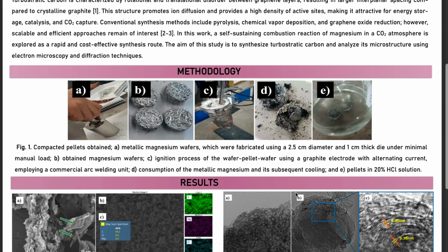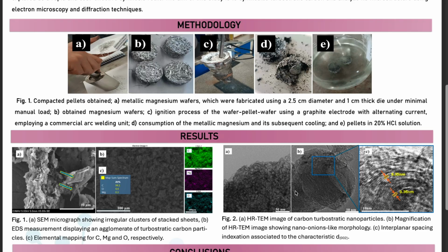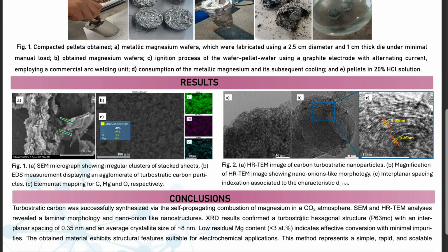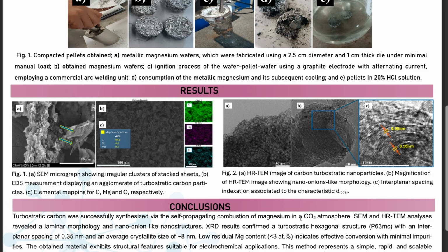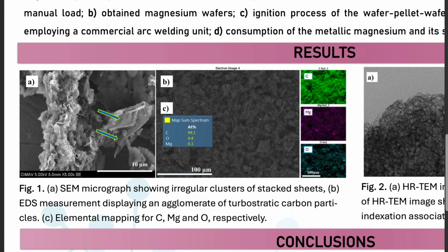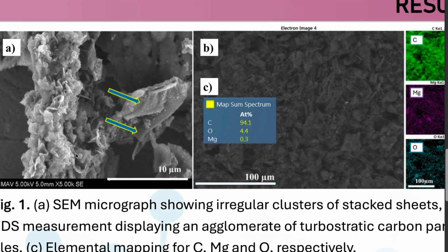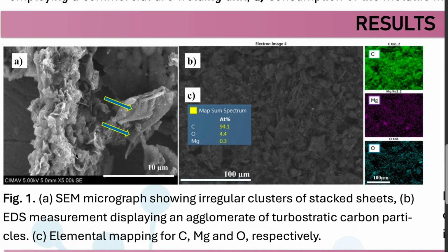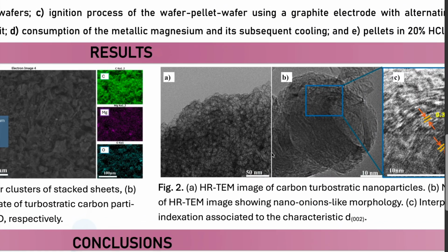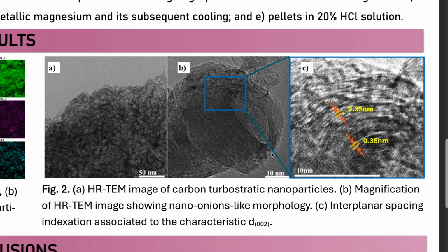Now, turning to the results section, we evaluated the structural and morphological features of the synthesized carbon. In Figure 1A, the scanning electron micrograph shows an irregular cluster morphology composed of stacked sheets. In Figures 1B and 1C, energy dispersive X-ray spectroscopy and elemental mapping confirm carbon as the predominant element, showing minimal residual magnesium and oxygen. At the nanoscale, high-resolution transmission electron microscopy in Figures 2A and 2B reveals a clear nano-onion-like morphology made of concentric spherical structures. This geometry provides high structural stability and a large surface area.